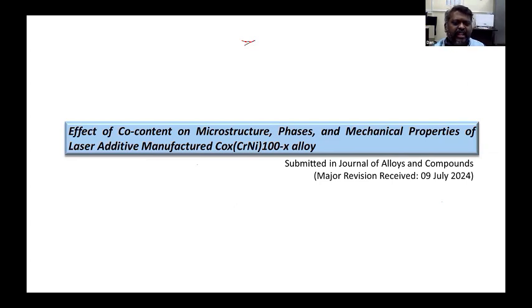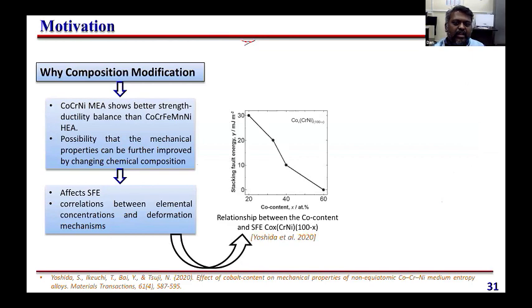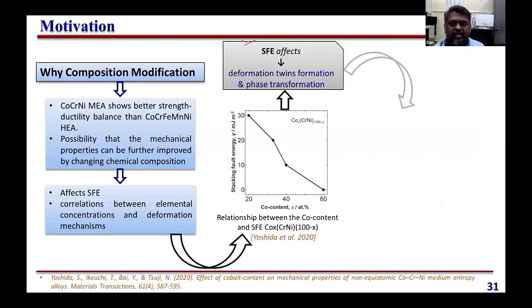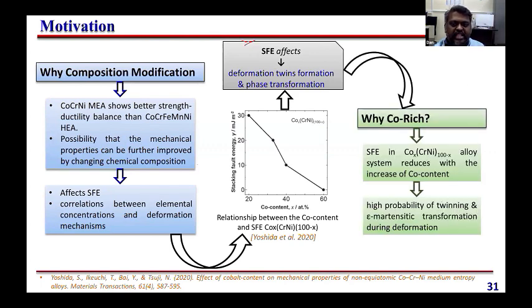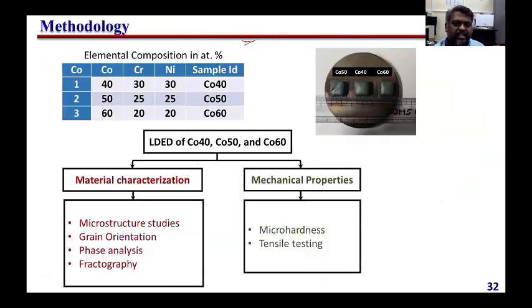And in the final, third case, we try to change the composition. We try to see how the cobalt content is affecting the microstructure, texture and properties in this laser additive sample. Why do we want to study this particular cobalt addition? Usually when we change the cobalt, it varies the stacking fault energy of the sample. When you change the stacking fault energy, the probability of twinning and some kind of phase transformation during deformation changes. That's why the probability of twinning and martensitic transformation is high when you go with a cobalt rich sample. That's why we try to increase the cobalt